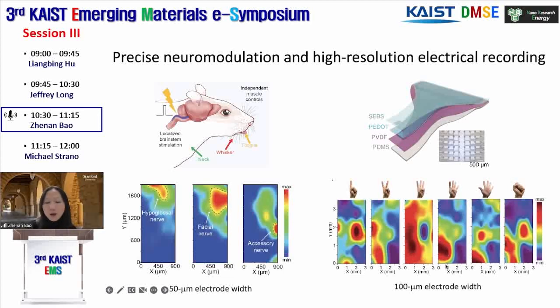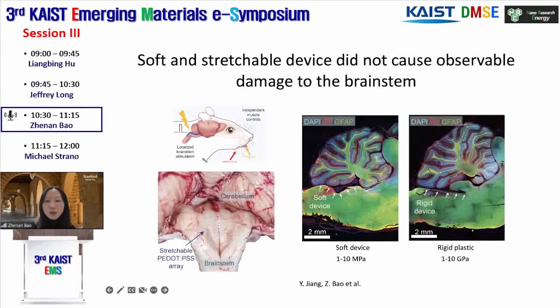And then for electrical recording, to highlight the importance of high resolution, we show the muscle measurement with 100 micron electrodes that gives highly different dynamics that can be mapped with such electrodes and provide details of single muscle fiber electrical signal. And to highlight the importance of having a soft device, you can see from this histology slice of the implanted electrode array, on the left is with the soft array. After a week or two, the histology still doesn't show any severe immune response or scar formation in this kind of device.